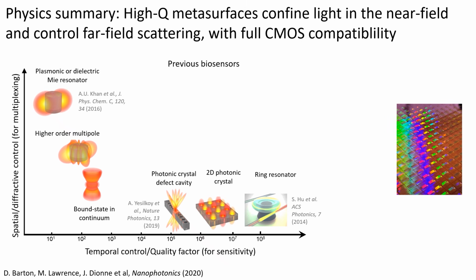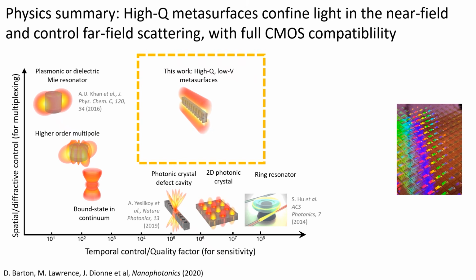And historically, there's been kind of a trade-off between these, and maybe some of you have heard about photonic crystals or ring resonators. Those are really great at storing light for extremely long periods of time, but they scatter light in all directions, and it's actually really challenging to get that one-to-one correspondence between what's happening where your molecule or your cell is and what you're actually seeing in the far field, like in a microscope camera. So we basically kind of bring the best of all these worlds together, where if you think about Mie resonators, those scatter like dipoles, but they're not very sensitive. But we've basically taken principles from nanophotonics, plasmonics, and then incorporated in those high quality factors.